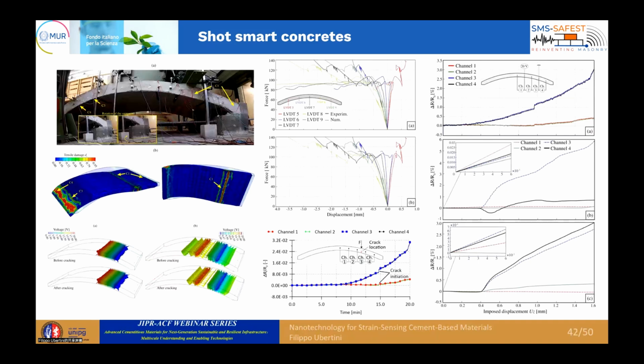Here is an output of the simulation. You clearly see that the collapse mechanism is the same as in the experiment. And here is a plot of the voltage distribution within the specimen. So in these graphs here, we compare with continuous lines and with dashed lines. It's not really well visible, but let me take a pointer here. Okay, like this. You can see here continuous lines and dashed yellow lines, same continuous blue lines and dashed blue lines, and so on, where the continuous lines are the experiments and the dashed lines are the simulation results. These are in terms of force displacements measured by the LVDT sensors.